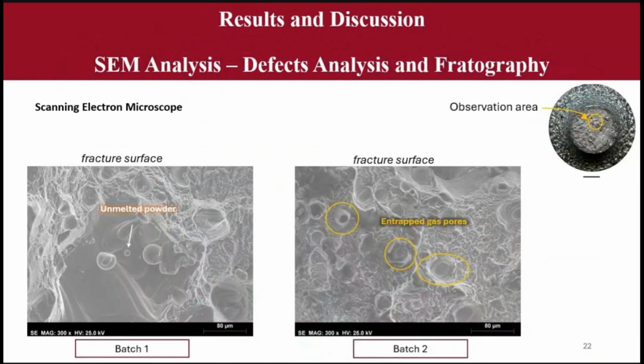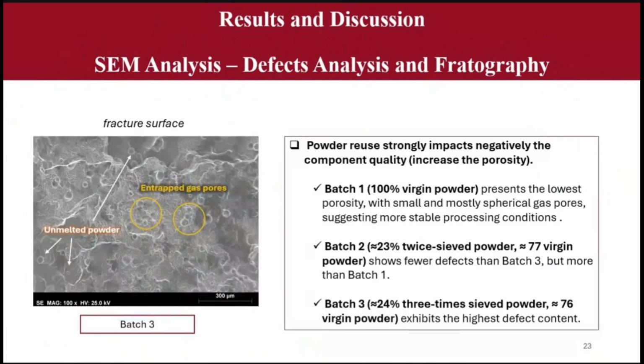Here was the SEM analysis, where we can observe unmelted powder and entrapped gas pores for batch 1 and batch 2. In batch 3, we can also observe more unmelted powder and entrapped gas pores. Batch 1 was virgin powder and presents the lowest porosity. Batch 2, that has 23% of twice sieved powder, shows fewer defects than batch 3 but more than batch 1, and batch 3, that has 24% of three times sieved powder, exhibits the highest defect content.